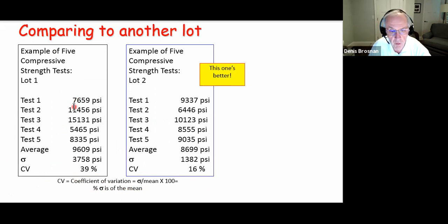And here are 2 sets of test values. These are compressive strengths, in inch-pound units. Let me get this right. We have 9609 pounds per square inch average in the first lot. We have 8699 average in the second lot. So if I only looked at average, I'd say the first lot was better. Stronger on average. So that sounds good.